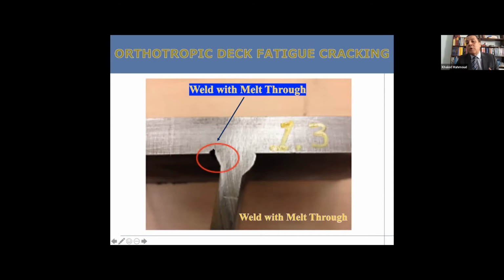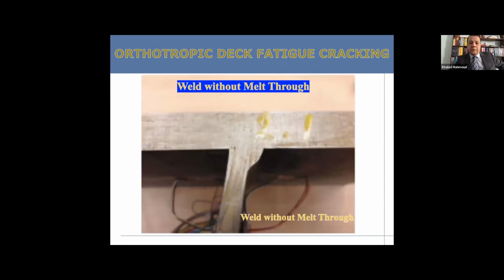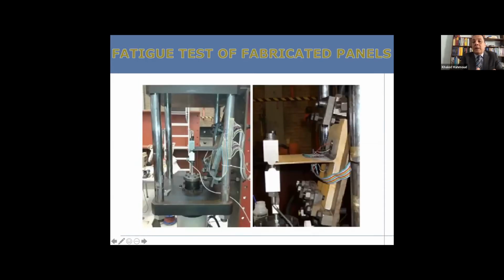The melt through is basically causing a crack-like defect, like what you see here circled in red, and that will start a fatigue crack here that would tremendously reduce the fatigue life of the bridge deck. Over here is another sample that we tested on a suspension bridge, where you have no melt through, and that was done with a setting of fatigue actuators, all instrumented to find out how many cycles, when the crack initiated, and how far it propagates, the whole nine yards of this.